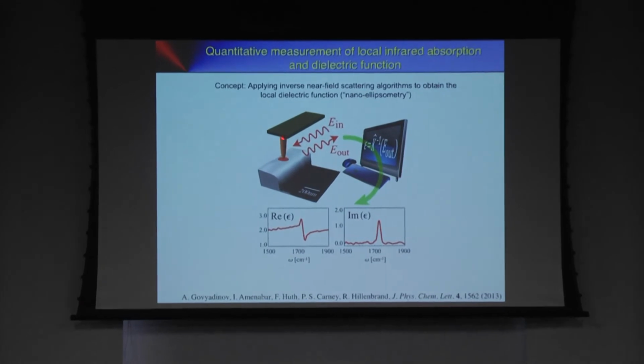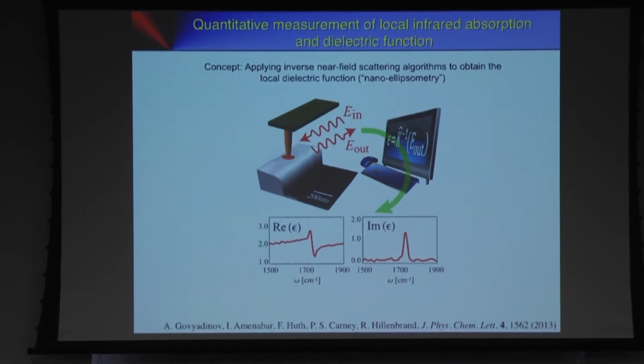Very briefly, the idea is that we also want to apply modeling and reconstruction. The first thing we did is we collect the backscattered light, and this is just some scattered light. We want to get epsilon out of it. The idea is the following, and it works. We take a model for this tip scattering process, and then we reconstruct the real and imaginary part of the dielectric function.